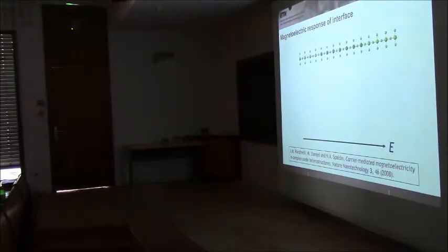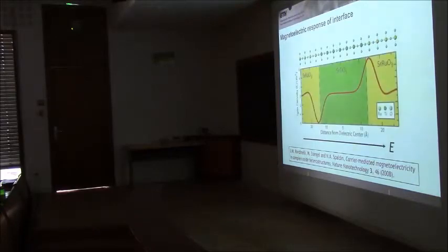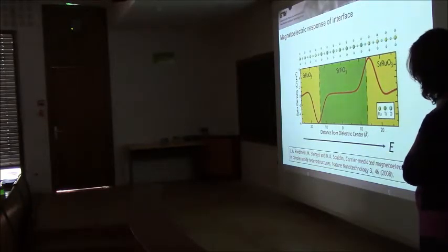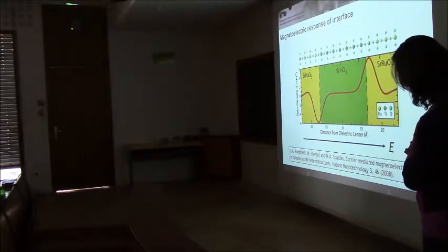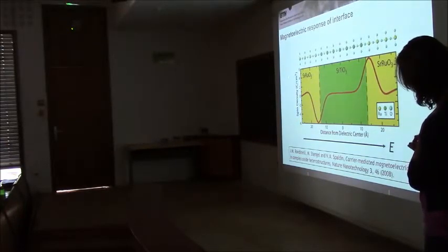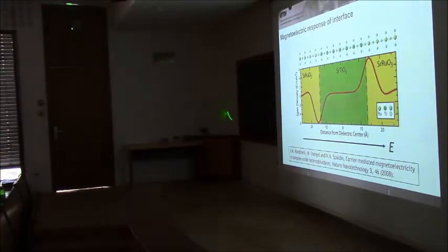And so then we built, in our computer, a heterostructure of strontium ruthenate with strontium titanate. This had periodic boundary conditions, so it's really infinitely repeated. And we applied an electric field in the calculation and calculated what happened for this response. Okay. And what we found was exactly as we expected. So this is the change in the magnetization as the electric field is applied. So spin density here should be change in spin density. Sorry, the strontium ruthenate starts off ferromagnetic, and this is now the change in the magnetization.